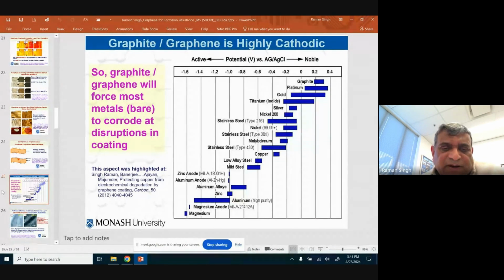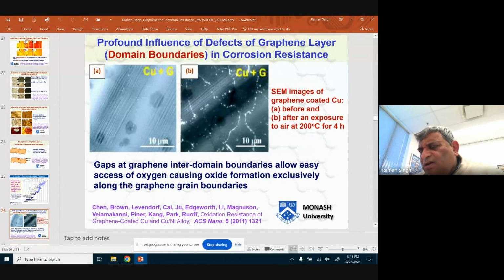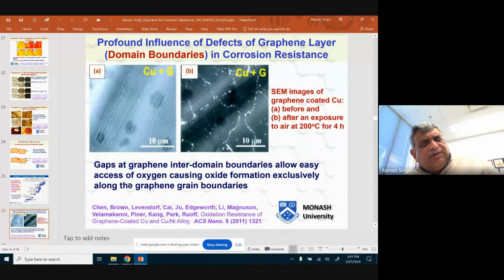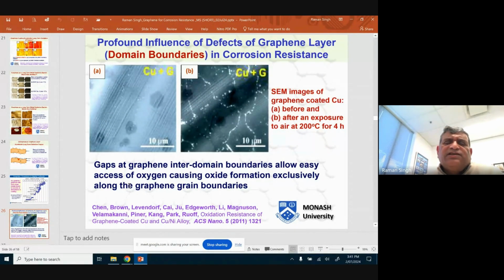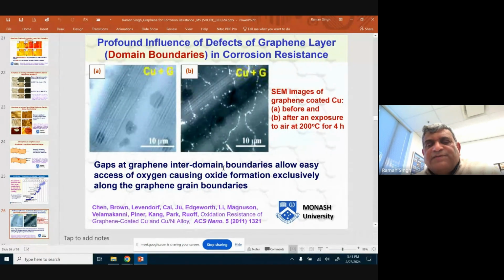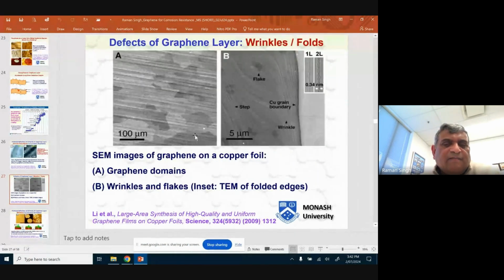Fortunately, in our paper, we had clearly mentioned that your graphene coating has to be continuous. That discontinuity is not the only problem with graphene. Graphene also has this problem of developing wrinkles. But before that, Rod Ruoff's paper also showed that wherever you have inter-domain boundary, corrosion was happening at that location at higher rate. So I was talking about wrinkles.